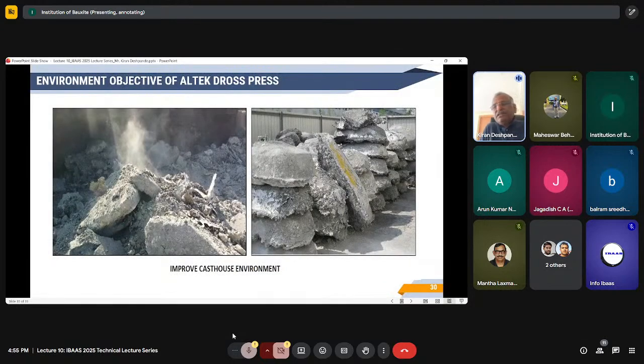Yeah, current conventional without dross press, you can see this mess. But after dross pressing, the skulls remain in well-mannered stacking positions. Now, these skulls have a lot of aluminum inside. On the left-hand side is dross left open. It has dust, hazardous fumes, and a lot of aluminum converted into aluminum oxide. And due to thermiting, a lot of aluminum goes into the atmosphere. So it's a big loss.